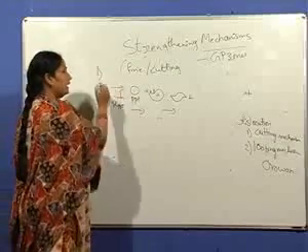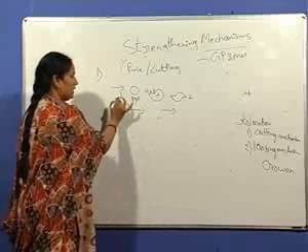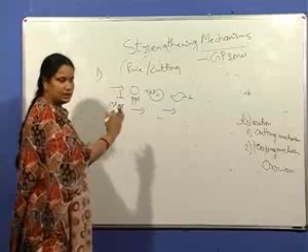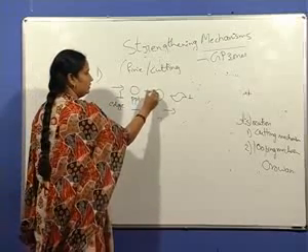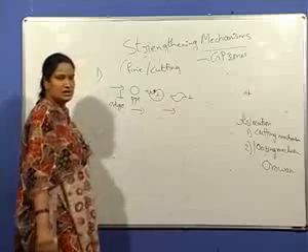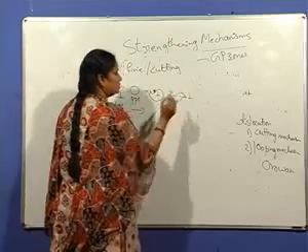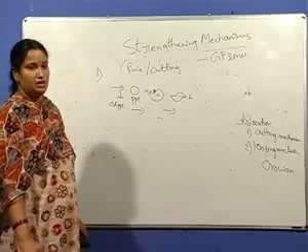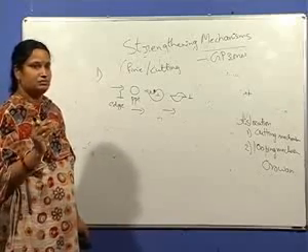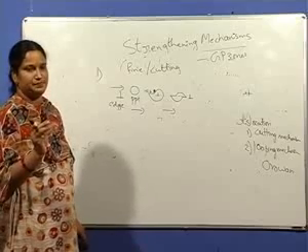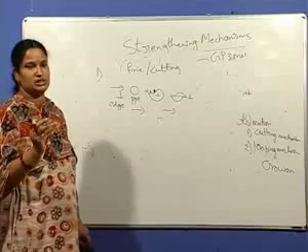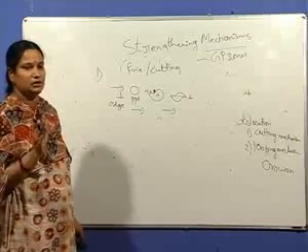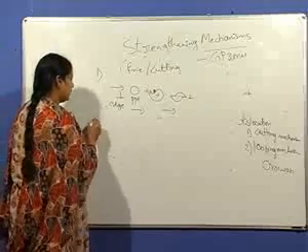One is the cutting mechanism, by which the edge dislocation, if it has to overcome the obstacle, has to cut the precipitate particle, which requires high stress. Thereby the precipitate particle has been deformed, sheared by the dislocation. When the precipitates are coarser in size, when they are not fine and cannot be cut by the dislocation, then the second mechanism that operates is the looping mechanism.